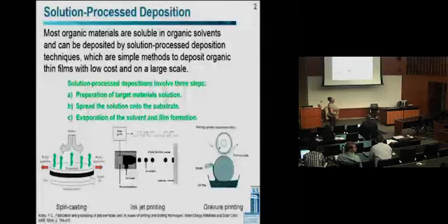And in general, by solution-based or solution processing, there are three very general steps that show up whatever type of solution-based processing you're doing. One is that you have to make your target solutions, whatever materials it is that you want to deposit. You have to spread the solution somehow on whatever your substrate is. And then you have to allow your solvent that you use to evaporate, and that has a big impact on what your thin film properties are.